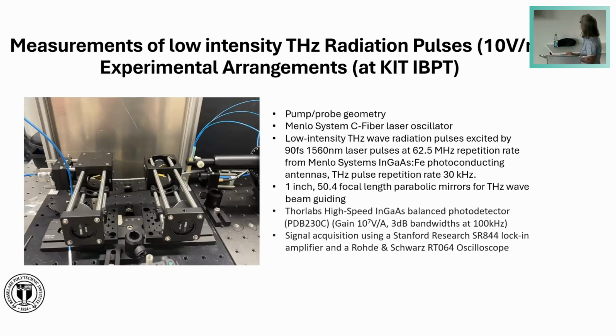Now here at the IBPT, we are looking at testing the sensor at very low intensities. We are basically at the other end of the electric field strength spectrum. Here we have approximately 10 or a few tenths of volt per meter. We also work in a pump probe geometry. We use a Menlo Systems C-fiber laser, which operates at 1560 nanometers and produces 90 femtosecond laser pulses at 62.5 megahertz repetition rate.